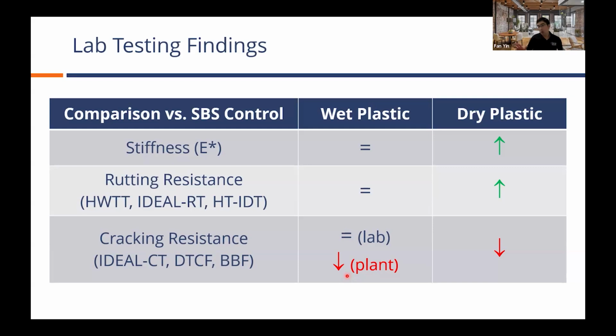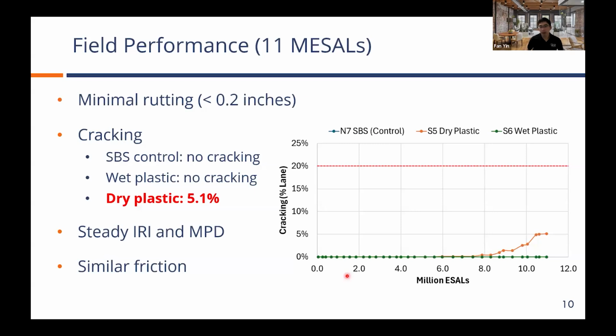Now you may wonder, hey, how do those sections perform at this point? Nathan mentioned earlier that the original plan was to go with one research cycle with 10-million ESALs, but after discussing with the sponsor, we decided to push for another cycle. What I'm showing here is the field performance up to this point. We are at around 12 million ESALs, but the data I'm showing here was from 11 million ESALs. Rutting was not a concern at all. We did not see any rutting issues or potential rutting concerns for any of these sections, which is as expected because our lab performance data indicated that.